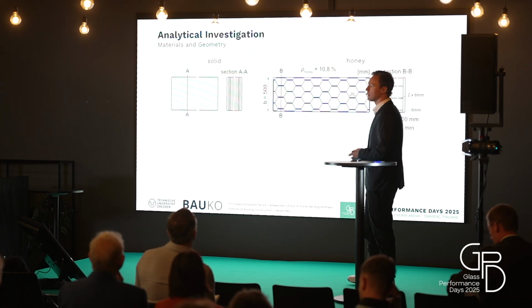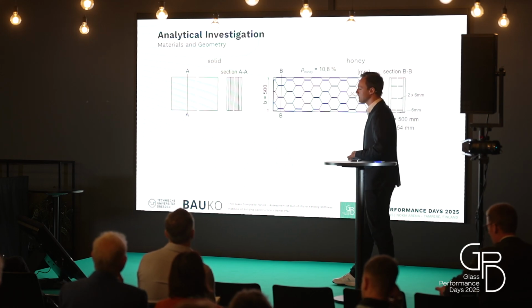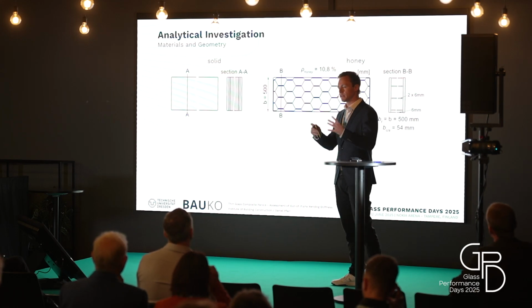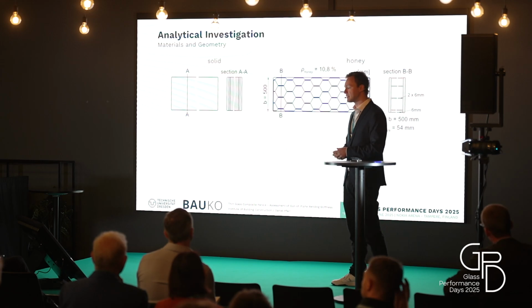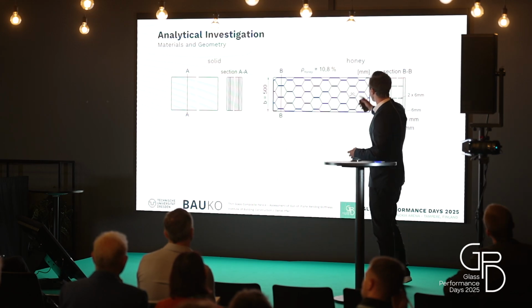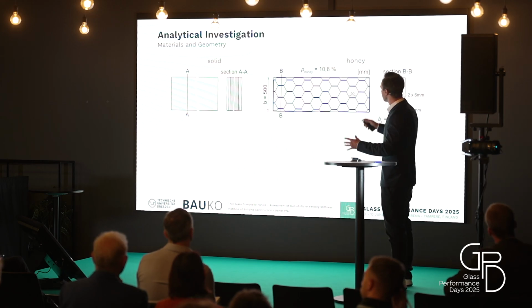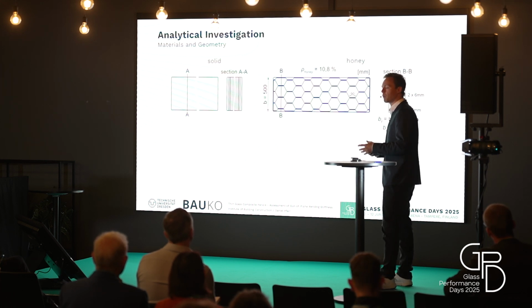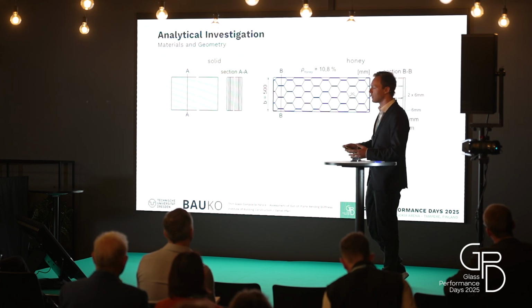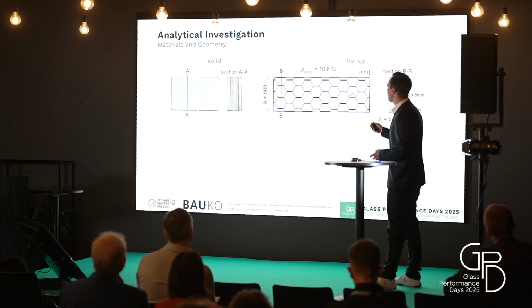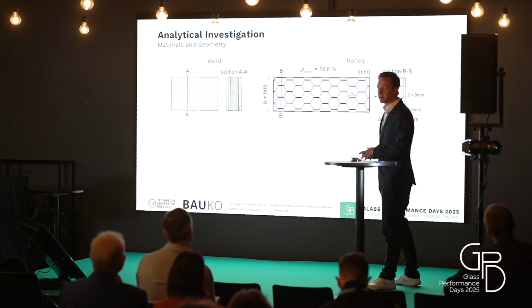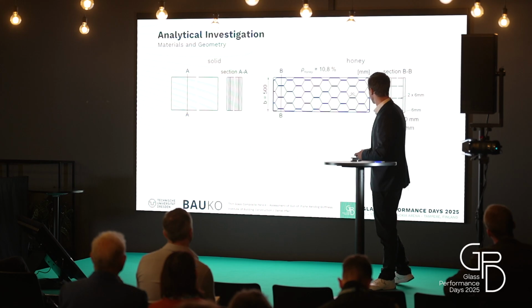Some materials and geometric basics here. So we have on the one hand side our reference, which is a solid core of polymer. So let's say 100% density. And on the right hand side, it is the honeycomb structure which we are using. It is representing the specimen for the experimental setup with a width of 500 millimeters and a length of 1,500 millimeters. And in that case, our density is 10.8% for the core structure.